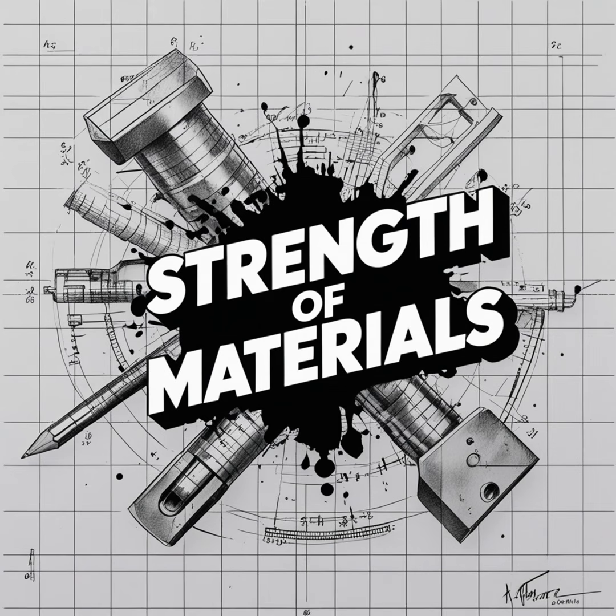Generally, for steels, this endurance limit hovers around 35 to 50% of the material's ultimate tensile strength. Okay, so about half. Roughly, yes. So if your steel alloy snaps under a static pull of 1,000 megapascals, its endurance limit for cyclic vibration will be somewhere around 400 to 500 megapascals. If you keep the vibrations below that, it runs forever.